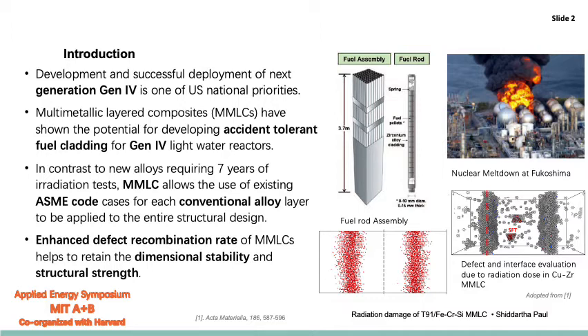However, developing new material for nuclear structural application requires numerous tests for establishing the ASME code for themselves. In this case, the MMLC can provide us a solution by decoupling the interaction between different established alloys through forming a functional graded material. In that way, we can use the existing ASME code for those particular alloys for the entire structure. Also, the alloys that we have used for this particular MMLC are iron, chromium, silicon, and T91.